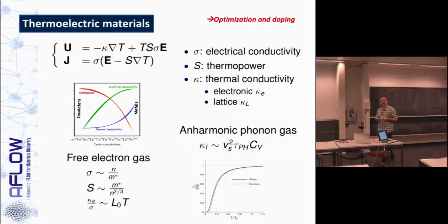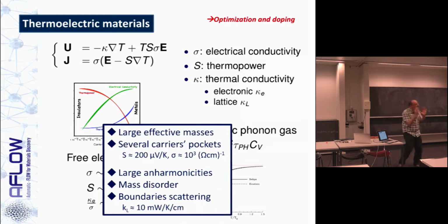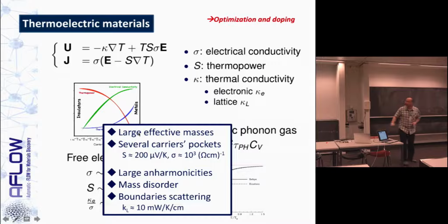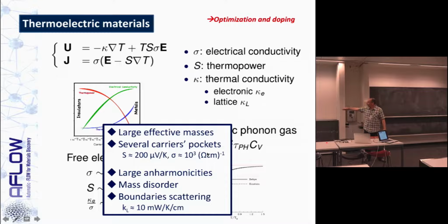Let me move on to a different model for high-throughput calculation, where instead of fixing a structure, you are fixing a specific material, but you are looking into paths to optimize the property of that material. The typical example is doping. I will not bother you with the basics of thermoelectricity, but in thermoelectricity, you need to deal with heavily doped material. And you're looking for materials that satisfy certain specific requirements. They need to have large effective masses, not too large, otherwise you're compromising the conductivity, but reasonably large. Several pockets for electronic carriers, and then large anharmonicity for mass disorder and boundary scattering for lowering the thermal conductivity. Okay? So this is a complicated task. It's very difficult.